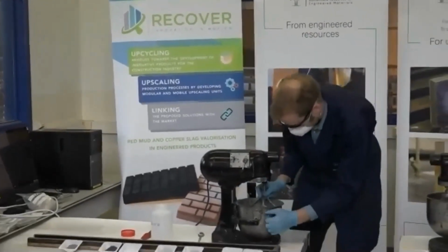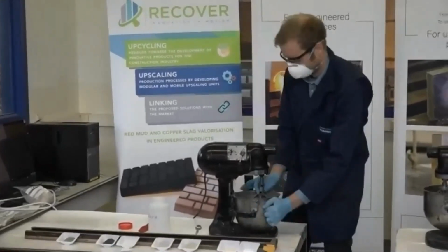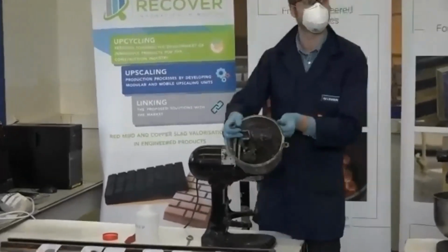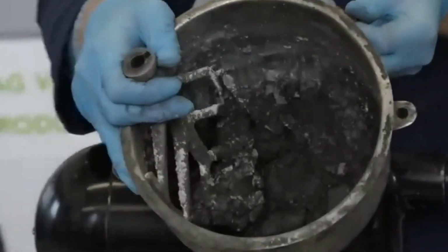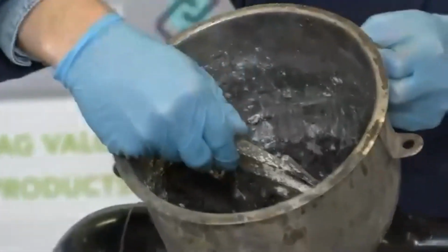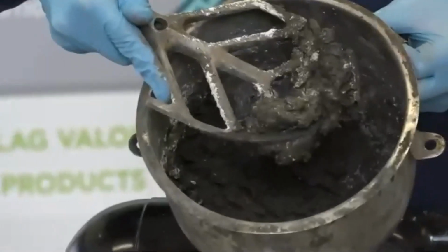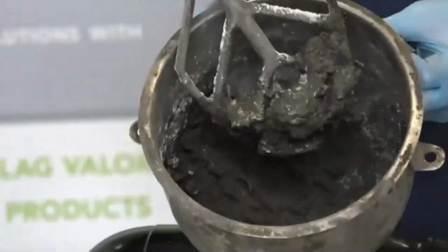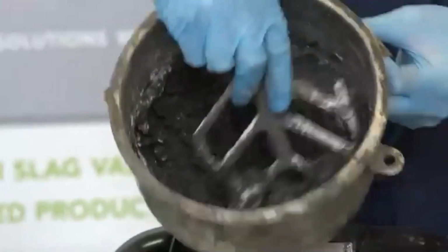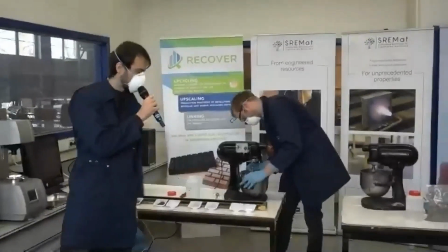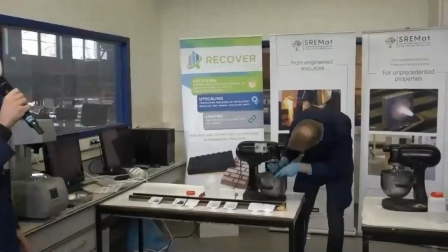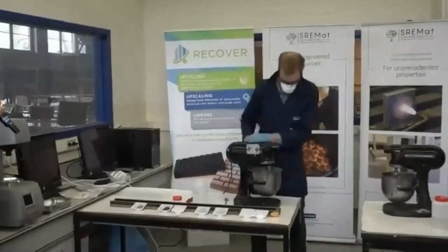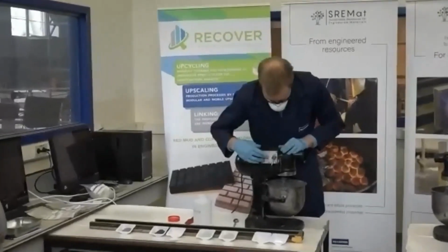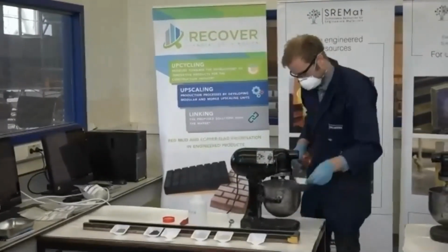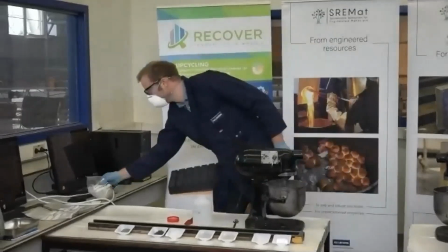Michiel will now show you how that paste looks. After just mixing the binders, the limestone and the activator, you see it's a very, very stiff mix. So you see he has problems moving it. What Michiel will do now is add these two additives that we have, which basically help us to increase the workability of the mix. These are typical additives which are also used in cement and concrete mixes to improve the workability of the mix.